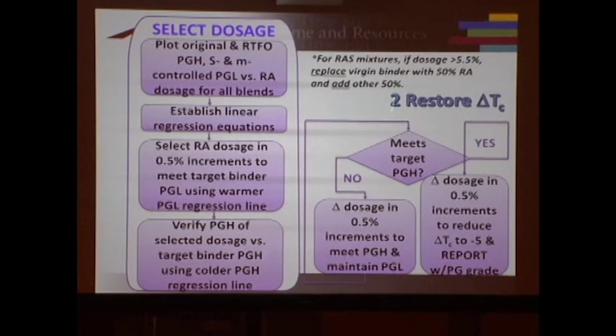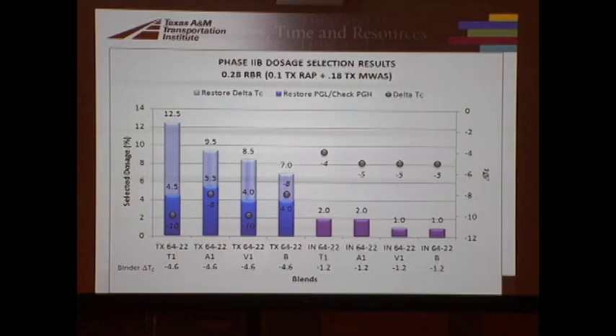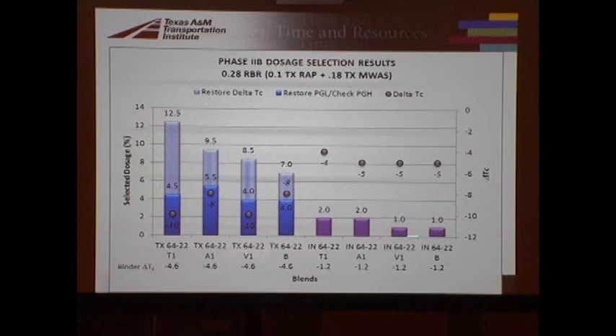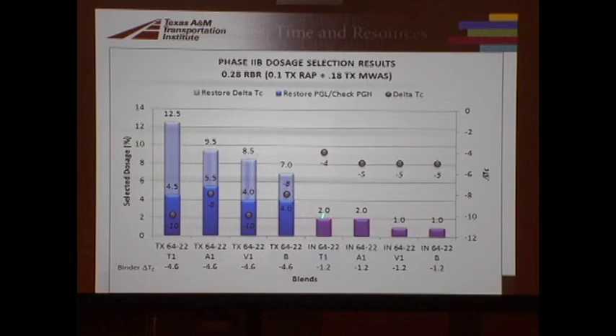So the second trial approach was, now let's try to restore the delta TC to that -5 threshold number. And when we do that, you see that that's the top of these. It goes from 4.5 to 12.5. So the example I showed you, you've got to really increase the dosage. And so when you do that, the Indiana blends, this is the better base binder with a delta TC of -1.2. The better base binder, it's already at -5 for delta TC. You see how there's no additional stacked element here. So the Indiana would have the same number whether we did it by trial approach 1 or trial approach 2.